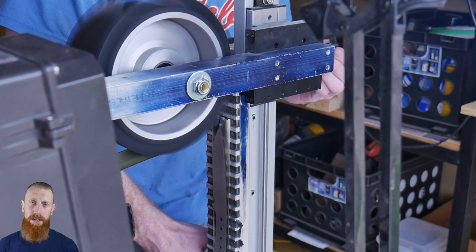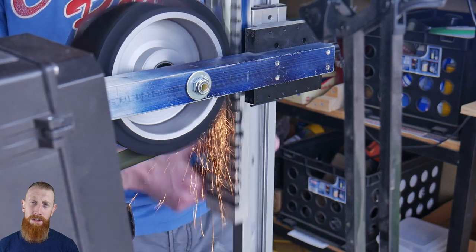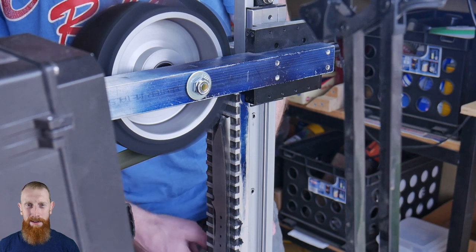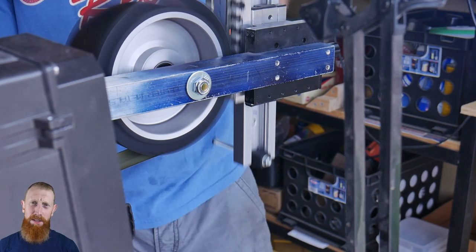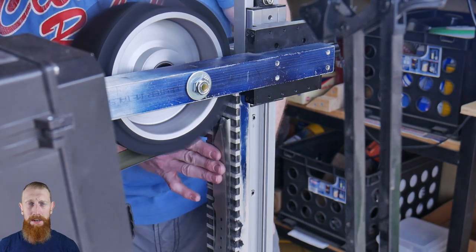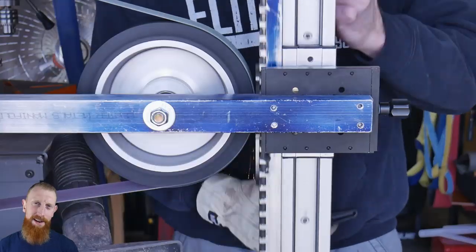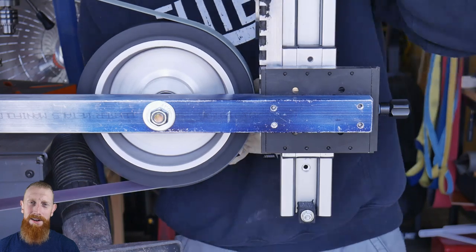After using this machine for months now, I can tell you that this is not a concern. The blade rarely gets up to a heat that is uncomfortable to touch with a bare hand, and the magnets don't even get close to that hot. In order to run the temper, you'd have to get the blade over the tempering temperature, which for me is around 420 degrees Fahrenheit, and I guarantee you my blades are not getting that hot on this machine.